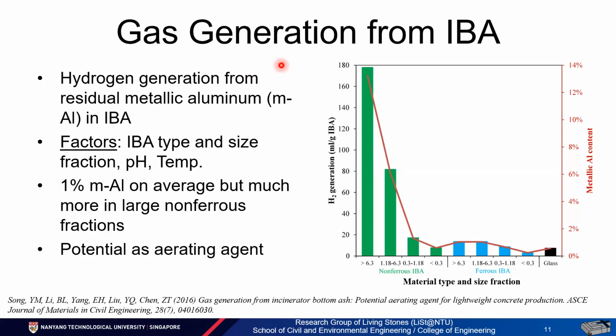Another interesting observation, because of the reporting of gas generation as shown before, we also identify that hydrogen generation from IBA at different size proportions and different types of IBA is not the same. That's mainly due to the presence of metallic aluminum, which when it interacts with alkaline solution will generate hydrogen gas.